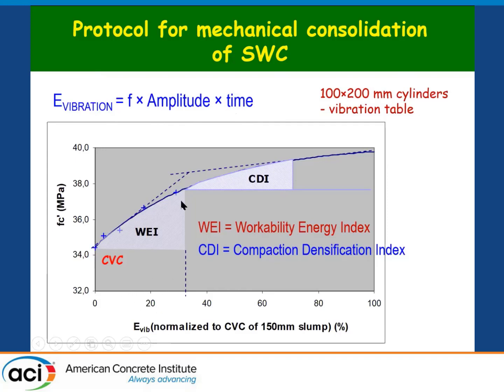We measured the compressive strengths, multiple points. And if the sample is not vibrated, you get, for example, 34 megapascal. And as you vibrate, the sample achieves higher compressive strengths. And if you keep vibrating, the rate of return reduces. But this is really what we call workability energy index, very important energy to consolidate and increase strengths, basically to densify the matrix. And the other one is a compaction densification index, is really to improve surface quality.